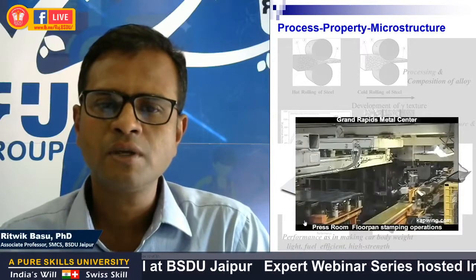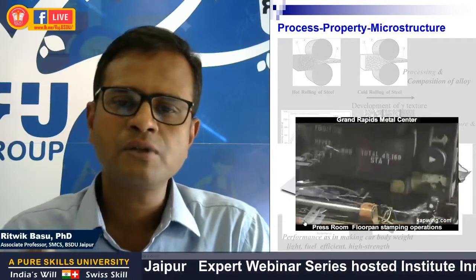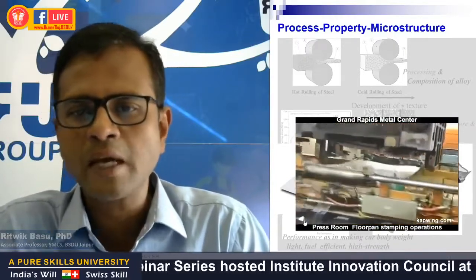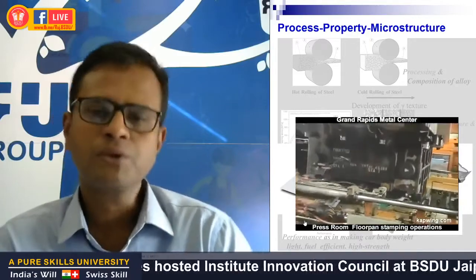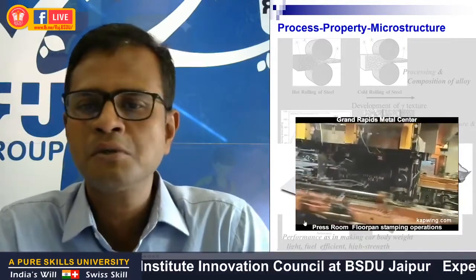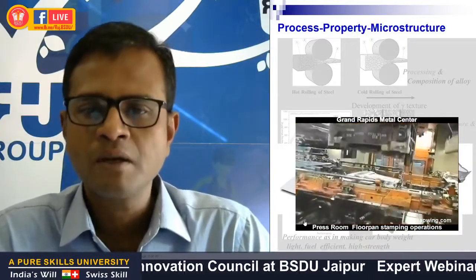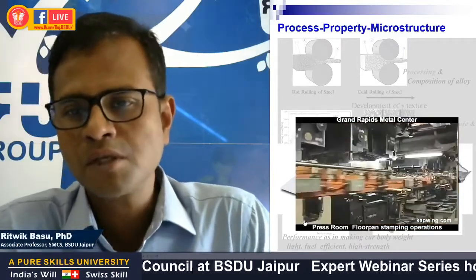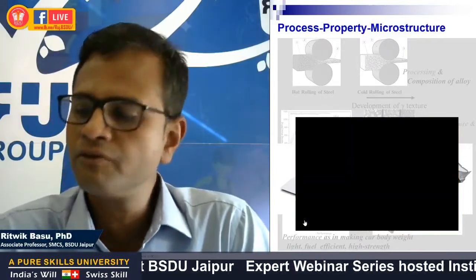So here I have a nice interesting video to show you how these sheets are processed in the industry manufacturing line. As you could see, the sheets are fed into a complex die mold arrangement, and typically a few thousands of pieces of the sheets are just produced in a few hours. But prior to this deformation, the sheets have been sufficiently annealed for a significant time and temperature so that it becomes soft and easy to deform in the next subsequent processes.